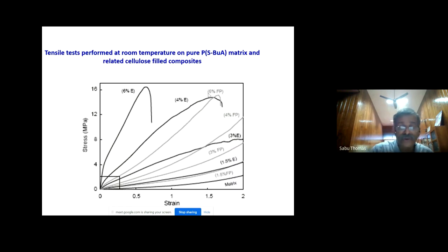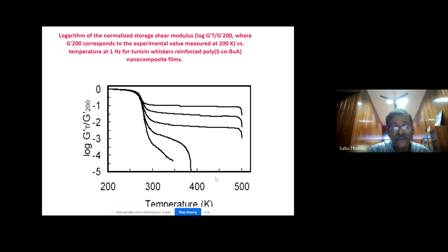And then we introduced nanocrystals into a biopolymer. Look at this, it is a neat biopolymer. And we introduced 5-6% of nanocellulose or nanochitin or nanostarch. You see, the mechanical strength goes up remarkably. This is with the 6% of nanocellulose. This is the neat polymer. Neat polymer is extensively rubbery. But when you put 6% of nanocellulose, the rubber is transformed into a high modulus material.